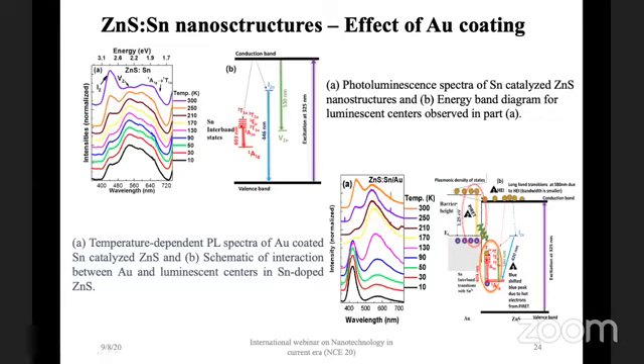We're still trying to understand it, and the only way is if we are able to do proper theoretical modeling of this phenomenon. Nevertheless, we have tried to explain schematically what is happening over here. So left side is the gold, and right side is the semiconductor, and we are seeing that we have hot electron injection coming from plasmons into the zinc sulfide, and they only participate with certain defect states, not with all the defect states. That's very important. So if they fill all unoccupied defect states, then we get quenching of these defect states, because there is no hole for these electrons to recombine. So that's what we observed over here.